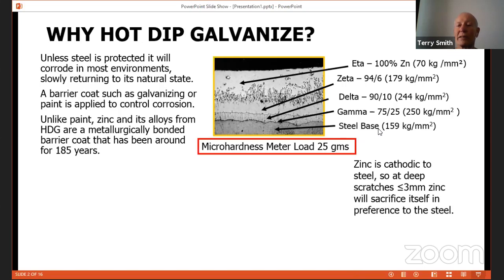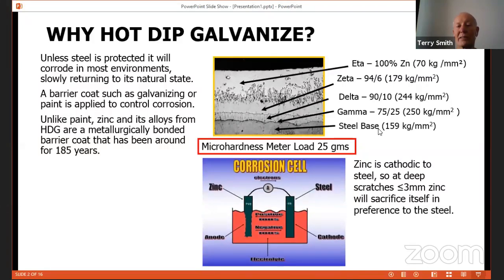Zinc is also cathodic to steel. So at a scratch of up to 3 millimeters, the surrounding zinc will preferentially corrode in favor of the steel. This can be seen here in the typical corrosion cell. On the one side, we see steel, which is the cathode. On the other side, zinc, which is the anode, placed in an electrolyte with an electrical connection, and those four things constitute the corrosion cell. So we use this technique, where the zinc sacrifices itself in preference to the steel.